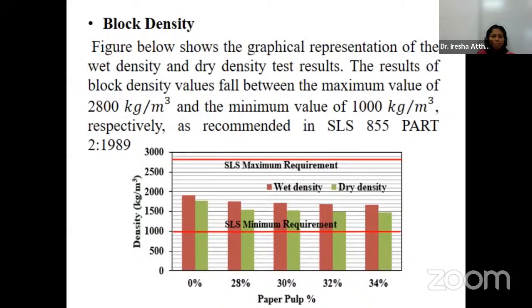Finally, the test for block density. Wet and dry densities of cement blocks were tested by obtaining wet and dry masses of cement blocks selected from each set of blocks cast from each mix. The test was conducted according to SLS 855 Part 2 of 1989. Here, the figure shows the graphical representation of the wet density and dry density test results. The block density values fall between the maximum value of 2800 kg per meter cube and the minimum value of 1000 kg per meter cube, as recommended in SLS 855 Part 2 of 1989.